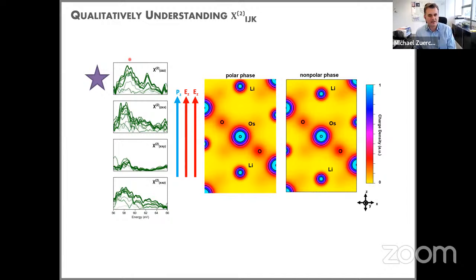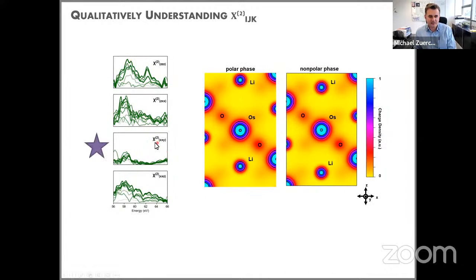In contrast, if you look, for instance, at the tensor component x, x, y, what does it mean? Well, a projection of the electric field along x, a projection of the second electric field along y, and the polarization projected along x. So this is what this tensor component encodes. You see, in this case, the crystal actually looks almost centrosymmetric. There's just very little asymmetry in this direction. So what you see here is that the second harmonic response is fairly weak as compared to the other component. This is just to illustrate that with proper planning, you can maximize the signal.